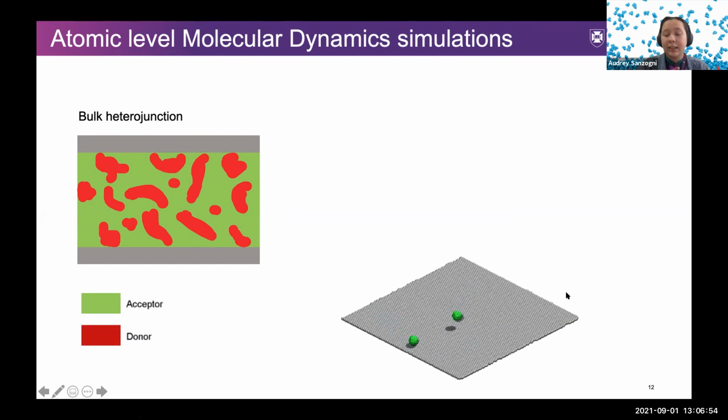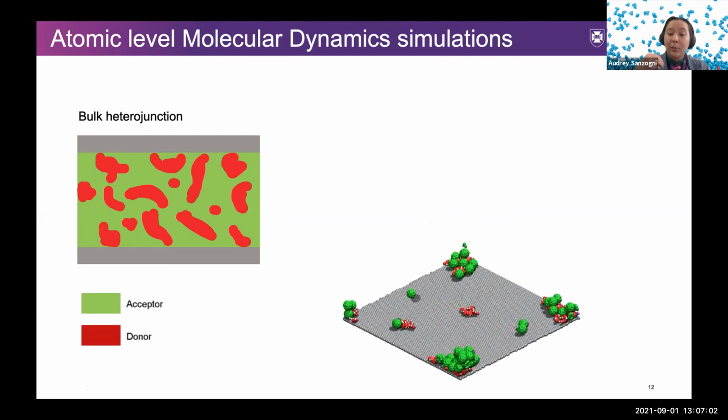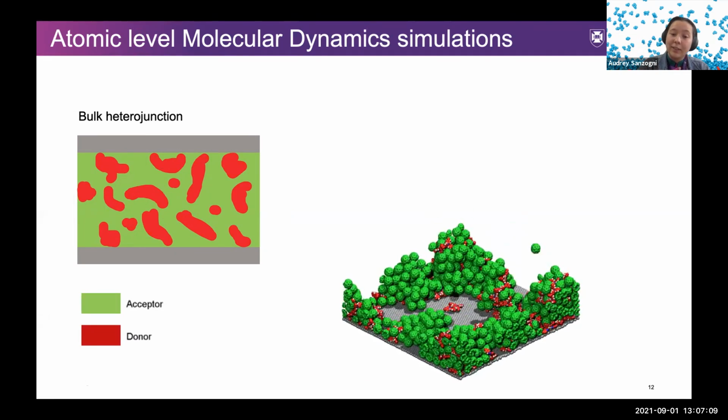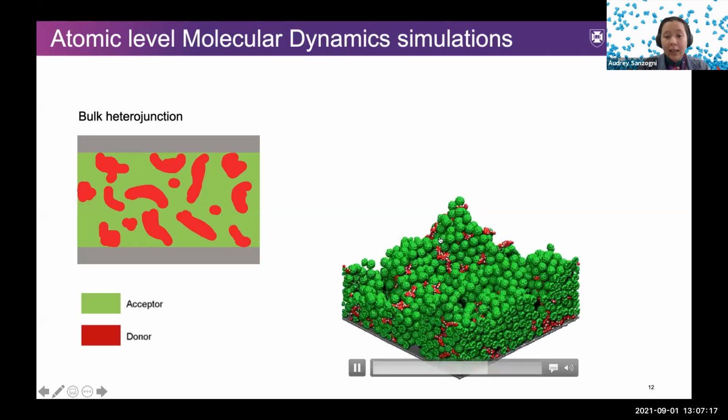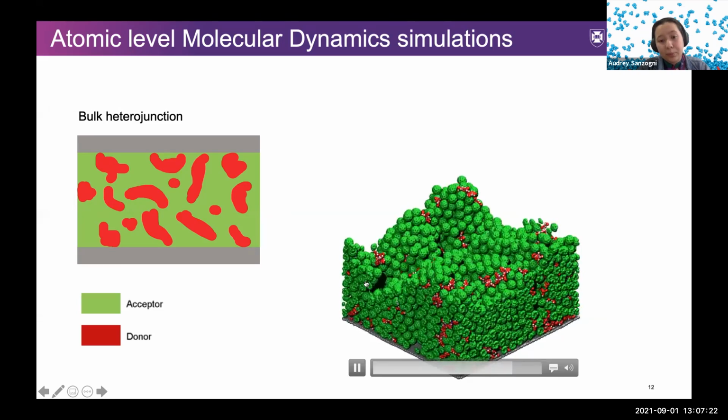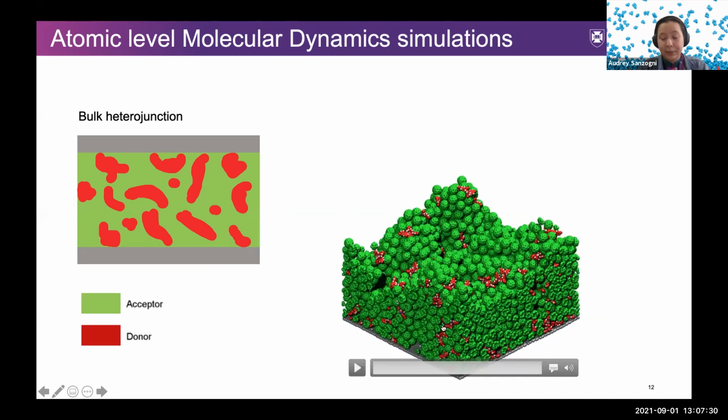Here we see the molecular dynamics simulation of the vacuum deposition of this device. You can see the buckyballs bouncing down off the graphene substrate and back up into the air. You can see that they have to cling to previously deposited TAPC first before they can grip on and start building the layer. You can see the roughness of the surface of this system and the pores that are being left behind. And also perhaps some circulation of the donor material throughout the system.